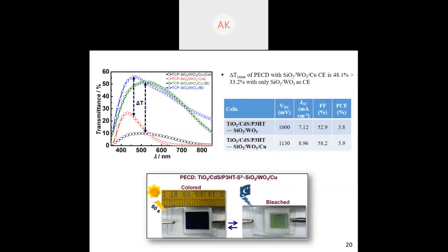Now, first I have tested for the optical part. Del T at lambda max of the PECD with SiO2 WO3 Cu counter electrode is 48.1%, which was much greater than 33.2 with only SiO2 WO3 as counter electrode. I have still kept SiO2 when I'm using pristine WO3. I don't want the WO3 to get dissolved in the alkaline electrolyte.